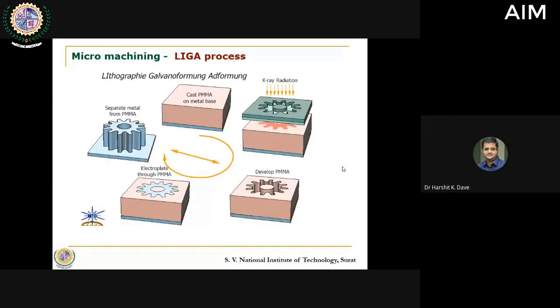What happens in it is you need to select a base material. Say for example, PMMA material is selected as a base material. So that is being created. Now it would be somewhat similar to the way we create a pattern and a mold. So this would be used as a mold. I use a photoresist, a mask, and then I pass the X-ray radiation. So whatever feature you want to generate, that feature is present over here. And because of this X-ray radiation, you create a specific cavity over here, and this cavity is opened up. Now here you use a certain electroplating process and you fill this cavity with the help of some desired material. It can be metal particles, it can be through metal deposition also. So that metal is deposited over here.